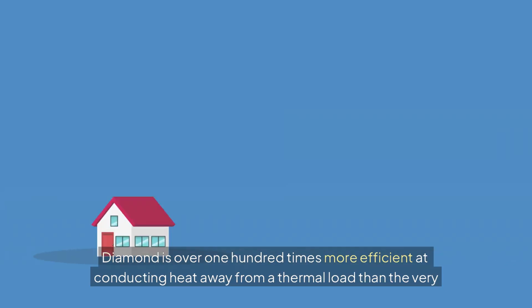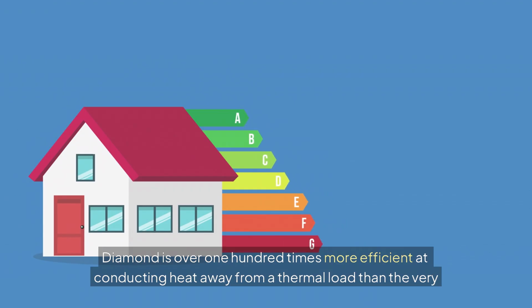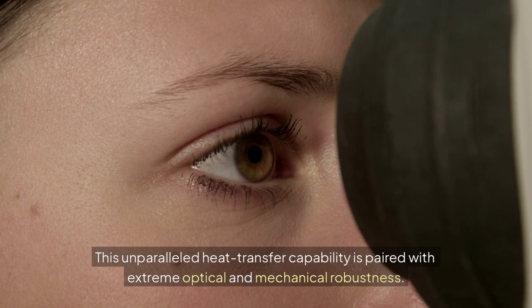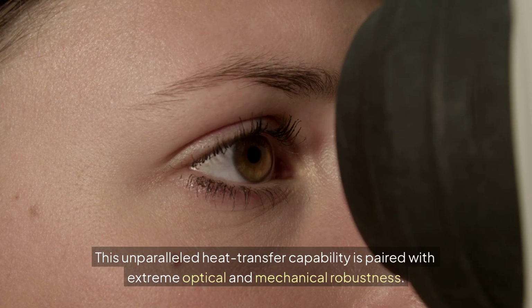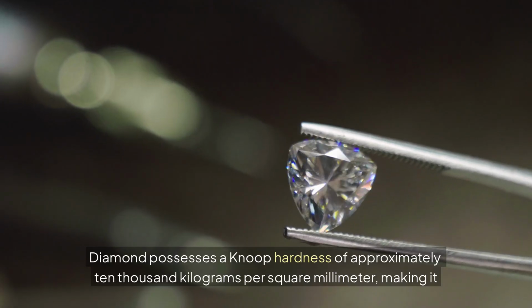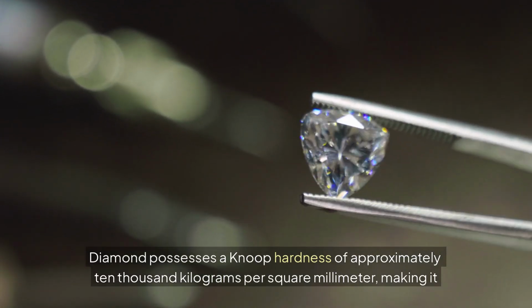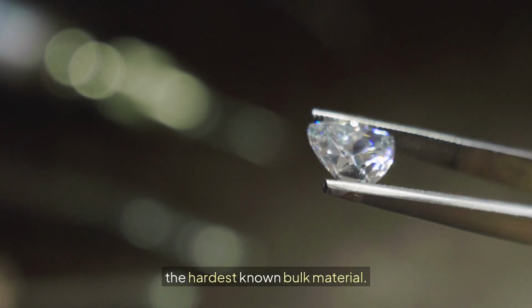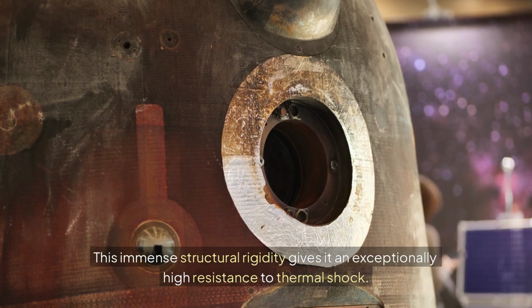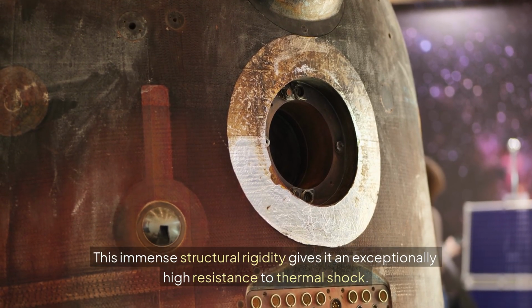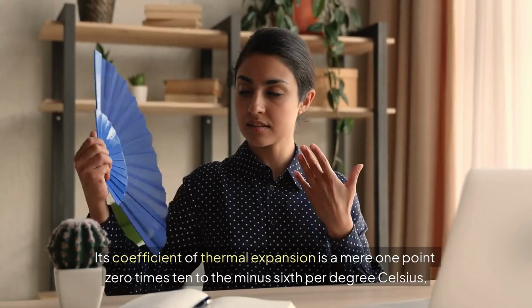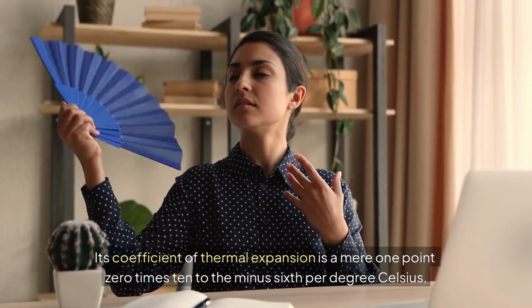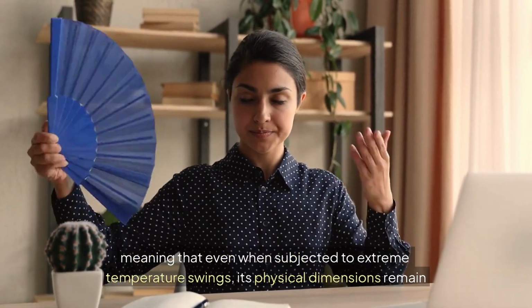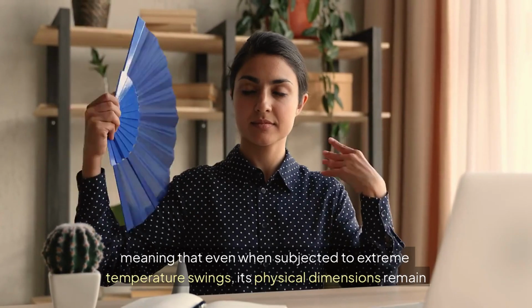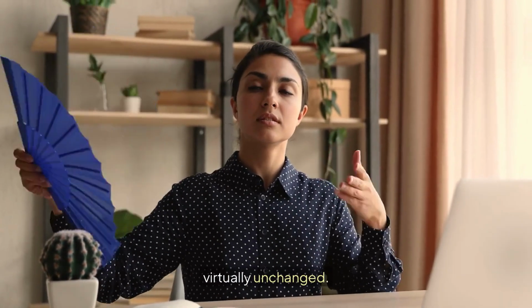Diamond is over 100 times more efficient at conducting heat away from a thermal load than the very material it is designed to replace. This unparalleled heat transfer capability is paired with extreme optical and mechanical robustness. Diamond possesses a Knoop hardness of approximately 10,000 kilograms per square millimeter, making it the hardest known bulk material. This immense structural rigidity gives it an exceptionally high resistance to thermal shock. Its coefficient of thermal expansion is a mere 1.0 × 10^-6 per degree Celsius, meaning that even when subjected to extreme temperature swings, its physical dimensions remain virtually unchanged.